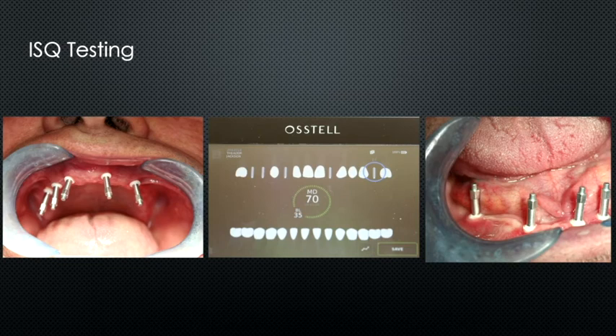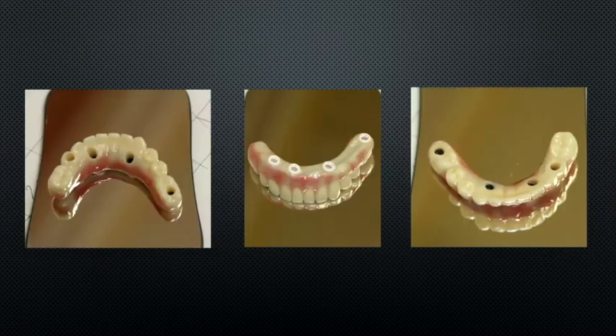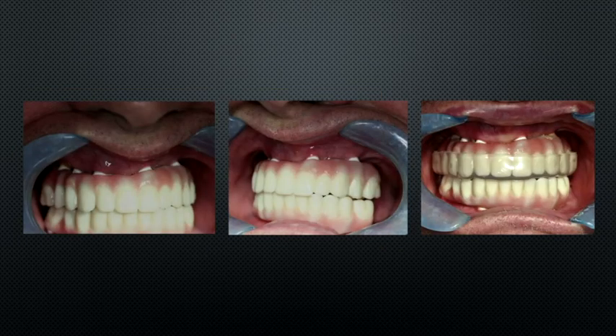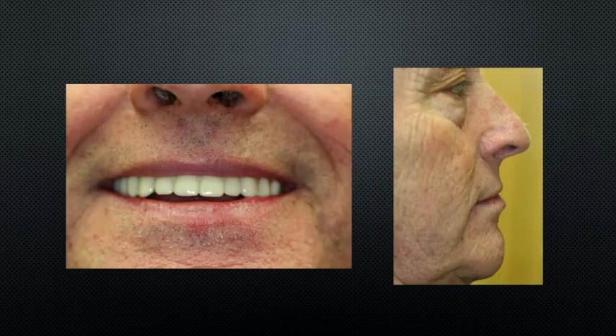You look for 65 and up. And once you have those readings on each implant, you're confident that the implant is well integrated and that you can restore it. And that's what we did. We did two hybrids, one on the upper, and that's what we have. All metal-free from the root to the cusp, and we give him a night guard also. Tons of hardware, and that's what it looks like at the end.